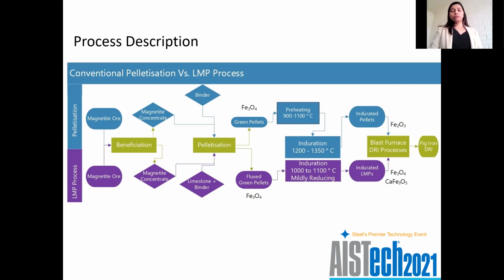LMP again starts with the beneficiation of magnetite ore to concentrate, and then during the balling stage, we add flux to form these fluxed green pellets. And then the fluxed green pellets go to a one-stage induration process at 1000 to 1100 degrees centigrade in a mildly reducing atmosphere. Mildly reducing because we don't want to oxidize magnetite to hematite, and it also ensures the formation of this CF phase, CaFe2O5 phase, which we have found improves the strength and reducibility of the LMPs at higher CF percentage. So these integrated LMPs with CF phase are strong and reducible enough to be charged to these blast furnace or DRI processes.